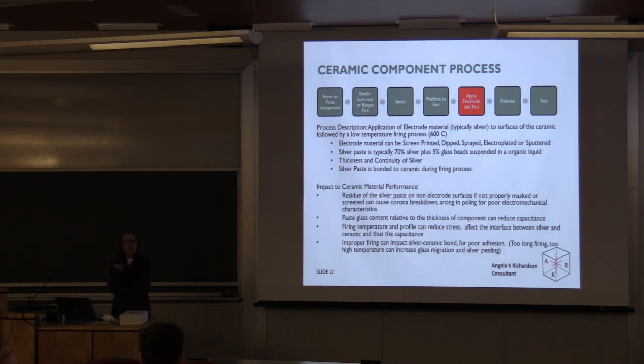The next step is, you probably saw in some of the ceramic that you have, it has a silver paste on it. And that's because we're going to solder wires to this ceramic, because it's an electronic component. So in that electroding process, we're going to apply a silver paste. The paste itself is about 70% silver metal, a little bit of glass beads, and then it's typically screen printed on, but it could be sprayed or it could be dipped, electroplated, sputtered, and then it is fired to make sure that there is adhesion between the paste and the ceramic structure.